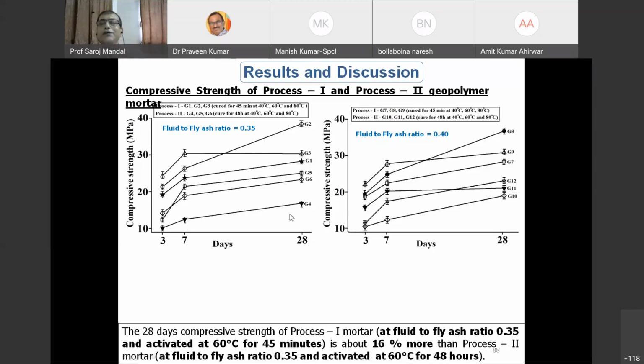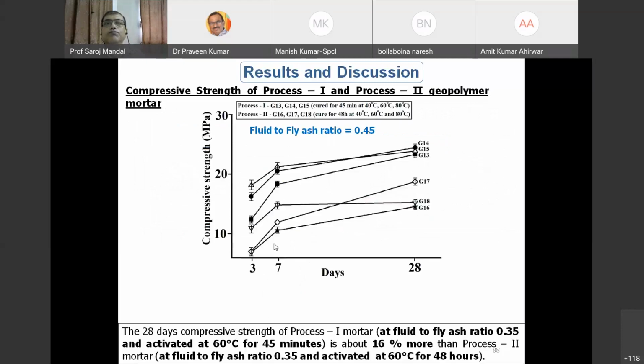So basically, for a particular fluid to fly ash ratio, process 1 always gives the higher values. Process 1 is basically G13, 14 and 15. So this is your process 1 and this is your process 2. If you see here, at all ages, process 1 gives a higher value compared to process 2. Right? Now, what is the reason behind it?